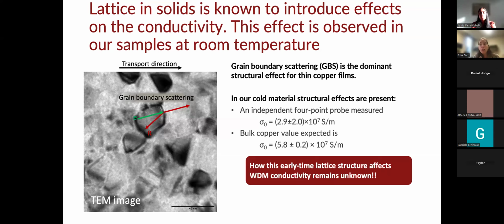Therefore, if you have a grain that is smaller than these 40 nanometers, what's going to happen is the electron is going to try to travel forward, it's going to encounter the edge of the grain, and it's going to scatter around. And this scattering, so these collisions that you will have, will decrease the conductivity because the electrons cannot travel as freely.